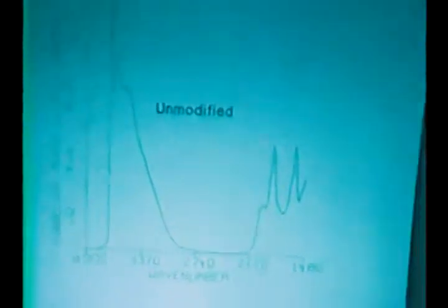After reaction with the hexamethyldisilazane, you see that the band at 3745 wavenumbers has disappeared. But the two bands from hydrogen bonded silanols remain intact, and here is the CH stretching absorbance from the trimethylsilyl groups from the HMDS. So interpretation of that reaction is relatively straightforward and kind of convenient.